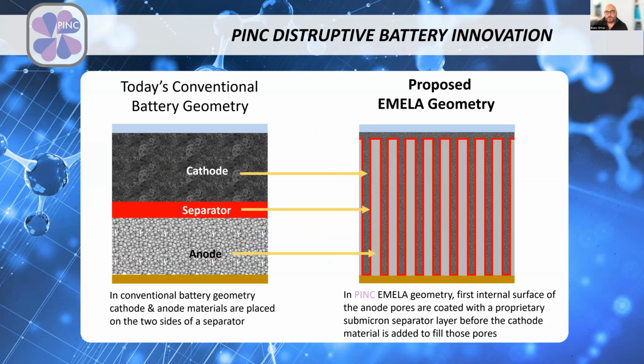What we are trying to do is, in this Manhattan and Brooklyn, instead of having people pass through a single bridge, we are giving every single one of them a bridge. Essentially increasing the surface area so much that the ions don't really meet with each other. The way we do that is to start with a porous anode, coat the pores of the anode with the separator in submicron thickness, distribute it all over the interface, and then fill the pores with the cathode material, as you see on the left-hand side.